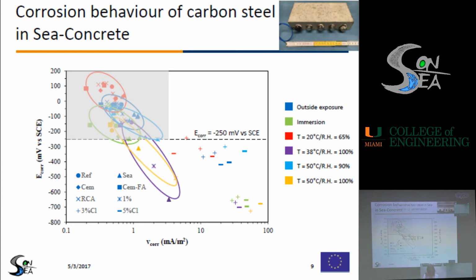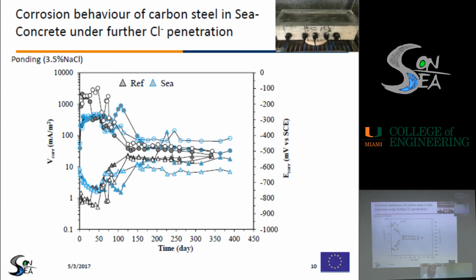These considerations were also confirmed when the specimens were exposed to further chloride penetration. As a matter of fact, other slabs were exposed to ponding with a chloride solution. This figure shows, as an example, the corrosion behavior of carbon steel bar embedded in the ref concrete, and we can observe that the corrosion potential, the circle symbols, decreases in time, and the corrosion rate increases in time. This was due to the initiation of corrosion. It means that the further chloride penetration induced the corrosion. So at the depth of the bar, the critical chloride threshold was reached, promoting the initiation of corrosion.